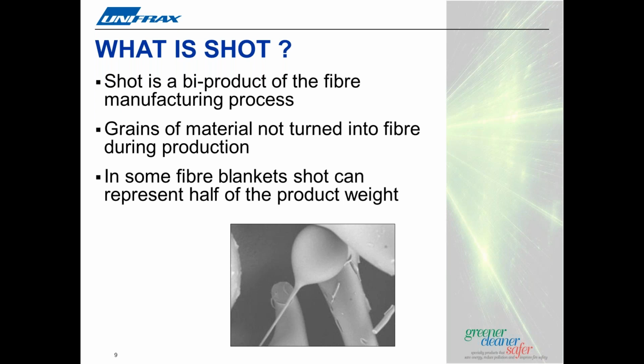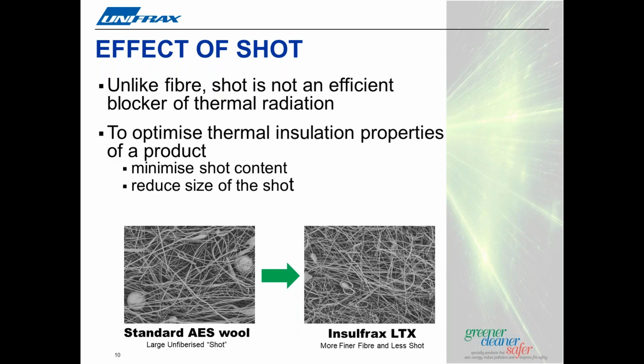In standard fiber blankets, shot can make up almost half of the product weight. But unlike fiber, shot is not an efficient blocker of thermal radiation. So to optimize thermal performance, we've not just reduced shot content, but also the size of the shot particles. Insulfrax LTX blanket typically contains up to 30% less shot than Insulfrax S blanket and 10 to 15% less larger shot.